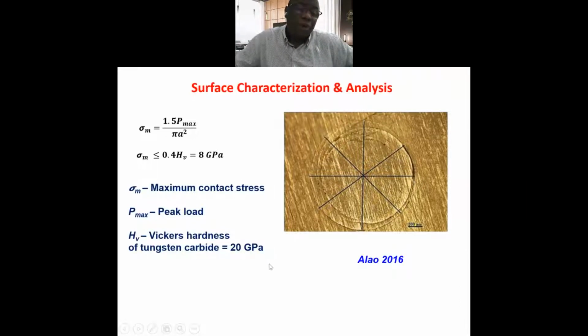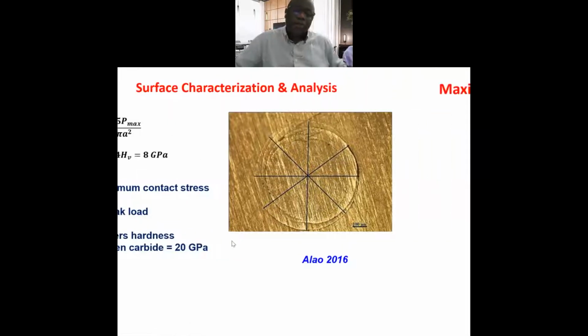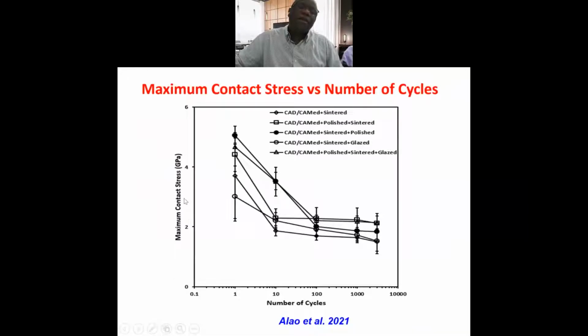And also for us to use this equation, it means that the maximum contact stress must be lower than or equal to 0.4 of the Vickers hardness of the indenter. In this case, we use tungsten carbide. The Vickers hardness of tungsten carbide is 20, multiplied by 0.4 equals 8 gigapascal. So the maximum contact stress must be lower than 8. According to this, none of the maximum contact stress is greater than 8. The maximum here is 6.